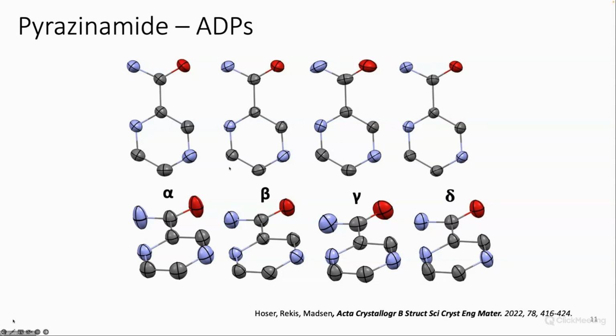Now, just from a glance, they look more or less the same, but if we go a little more into the details, perhaps we can see that the alpha form and the gamma form actually have slightly larger ellipsoids than the beta and the delta form, which could allude to the fact that they are also more stable. They have a higher level of vibrations in the crystals, so perhaps the vibrational entropy of those could be higher, and that could be a determining factor for having a higher stability at higher temperatures. So this analysis is of course very hand-waving, and we would like to do something a little more solid than this.